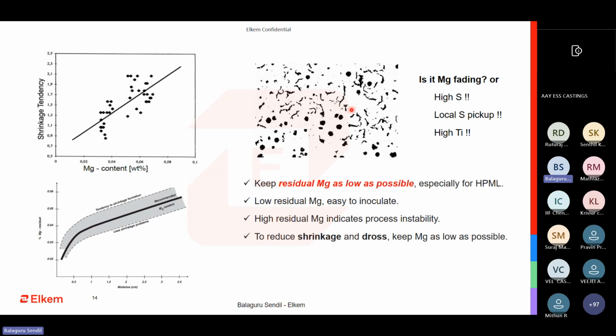Magnesium fades very, very late. You do not typically see ductile iron fading for 12, 13, 14, 15 minutes after treatment. It is not from the point of tapping. After treatment, people pour for 12, 13 minutes. The pouring is only restricted because the temperature loss is so high that you might end up with cold laps. The fading is not so high.